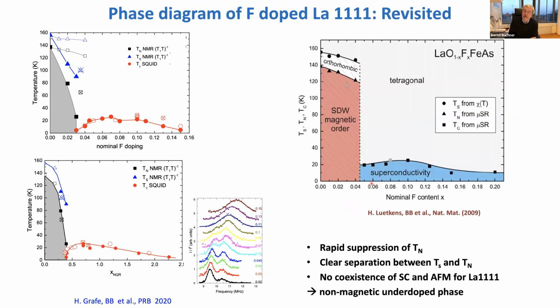Let's have a close look at the phase diagram, which has been known for more than 10 years, an old work by us. We have revisited this also for powder samples. What is known is that we have a very strong suppression of the magnetic ordering or the structural phase transition. And this is also seen in the more recent data. Now, meanwhile, we managed to get a smaller TN down to 30 Kelvin. So it's not this first order-like behavior, at least not for the magnetism. There we can follow it down to lower temperatures. But there is still a clear separation between magnetic order and the structural phase transition. And so the nematic phase transition and the magnetic one are well separated.